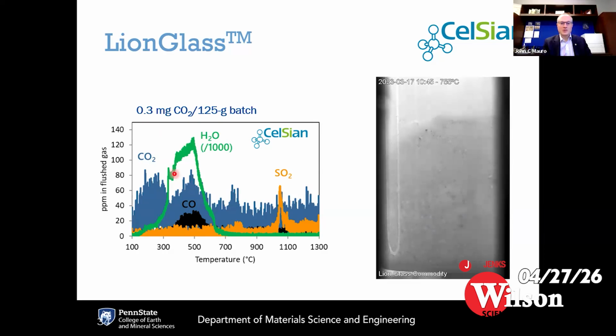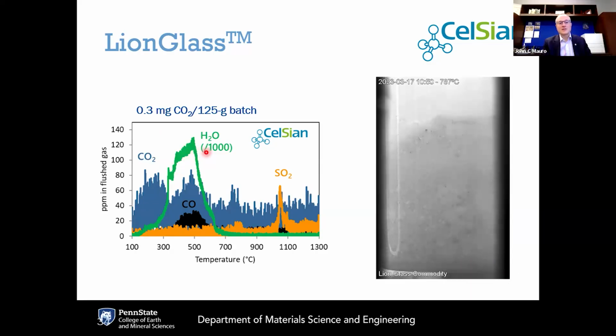Instead of CO2, the main gas that gets released is water vapor. This is the water vapor concentration divided by 1,000. It is important to have gases that get released because that helps with the homogenization of the melt. So what we're doing is trading something that's environmentally harmful, CO2, for something that is environmentally neutral, H2O. This SO2 peak is just due to the fining agent, the same as in soda lime.